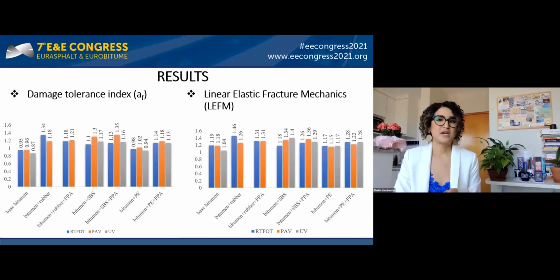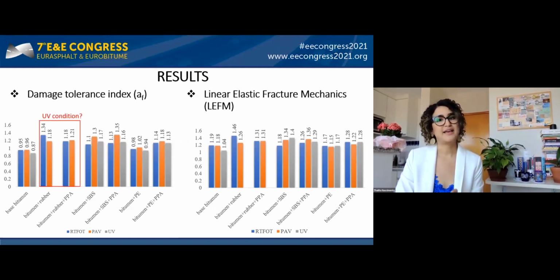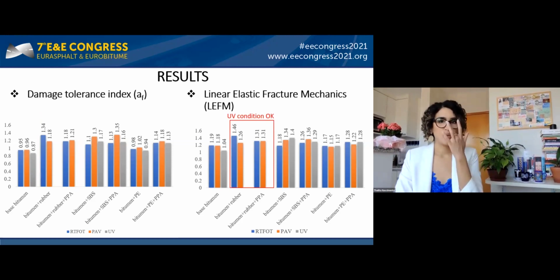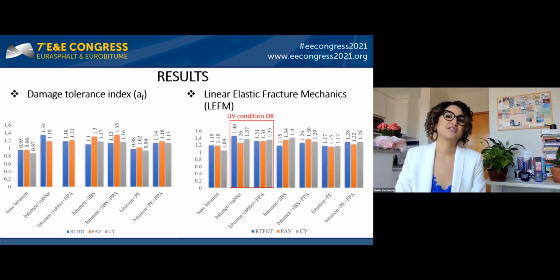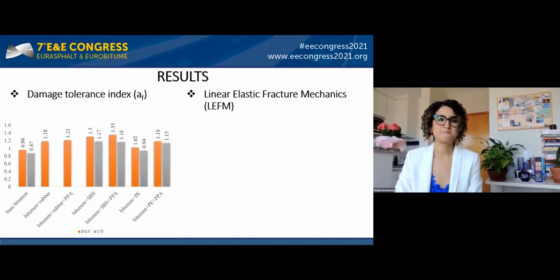The results that could not be obtained from the Af parameter were obtained using the LEFM approach, which showed to be effective given that all materials had their crack length at failure determined. By comparing the results for PAV and UV aging, it's possible to observe that all samples aged in PAV presented a higher tolerance to damage when the parameter analyzed was the Af.